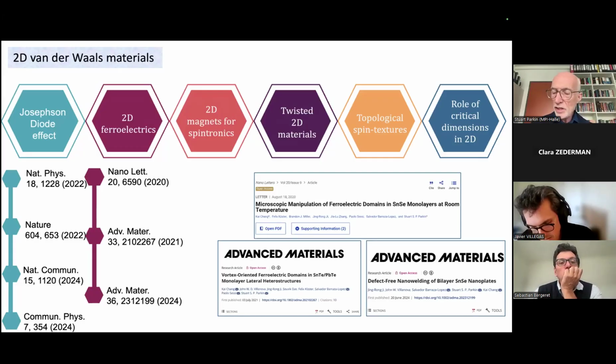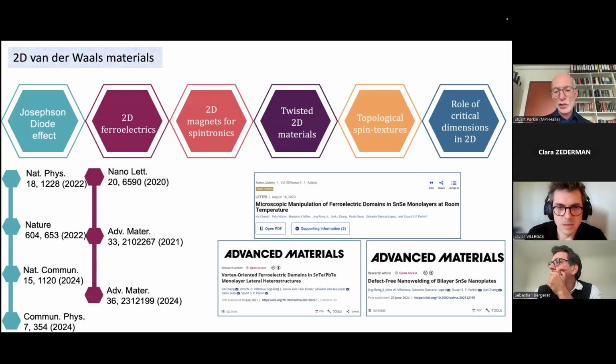And recently we've demonstrated what we think is a very interesting tunneling junction between 2 ferroelectric domains oriented with their polarizations in distinct directions, separated by a paraelectric lead telluride. And the lead telluride is just a few nanometers wide.